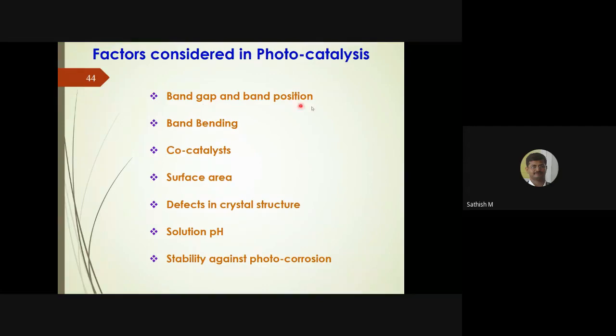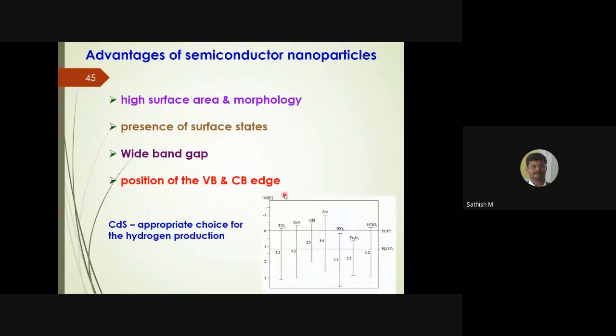The band gap and band position, how the band bending occurs, what kind of co-catalyst you are using, what the surface area is, the defects in the crystal structure, what the pH is, and the stability against the photocatalyst, or the photocorrosion. This point I think is more important. Though some of the catalysts are well known, they are very susceptible to photocorrosion.